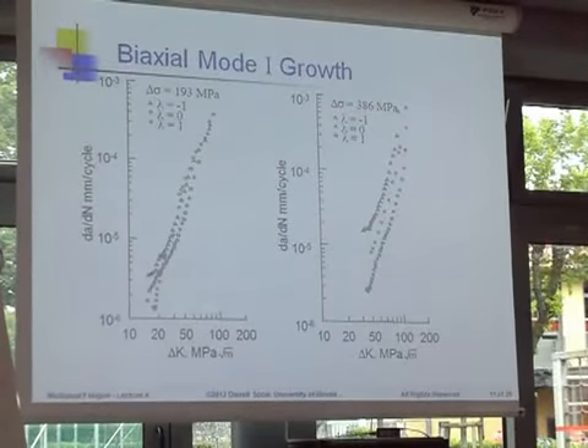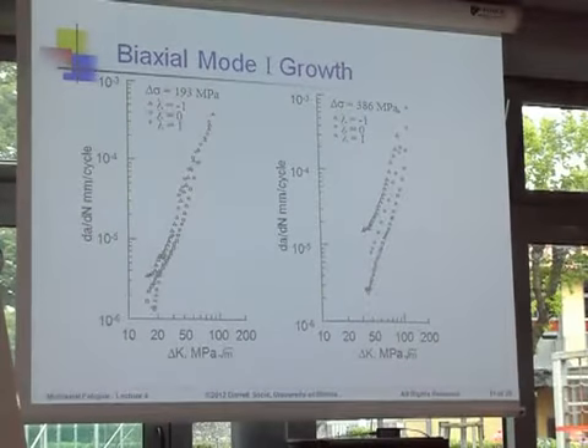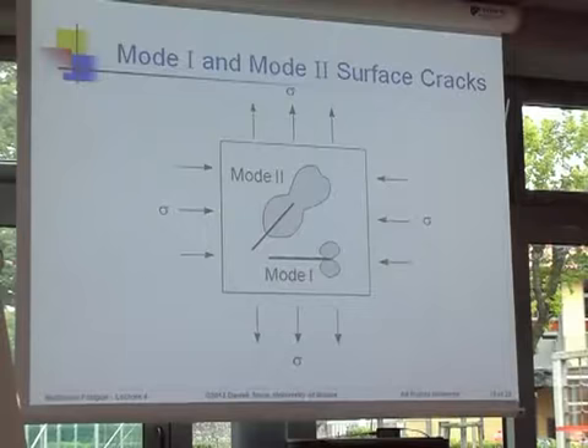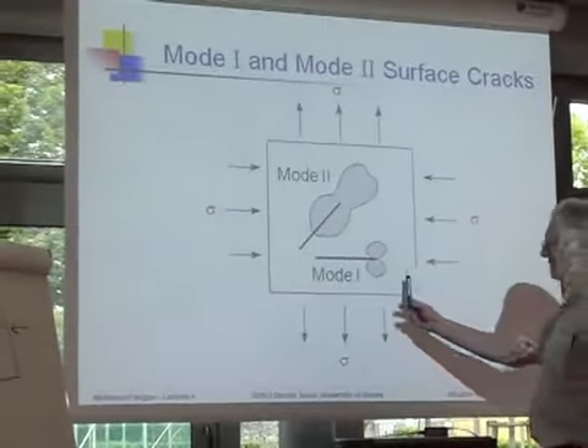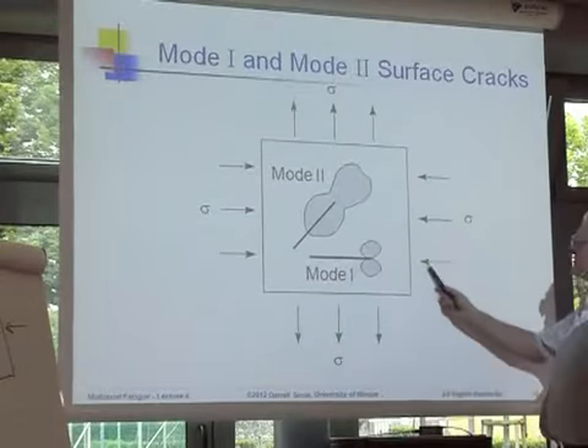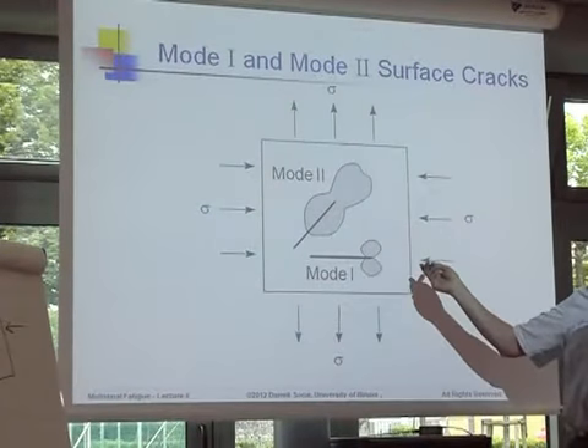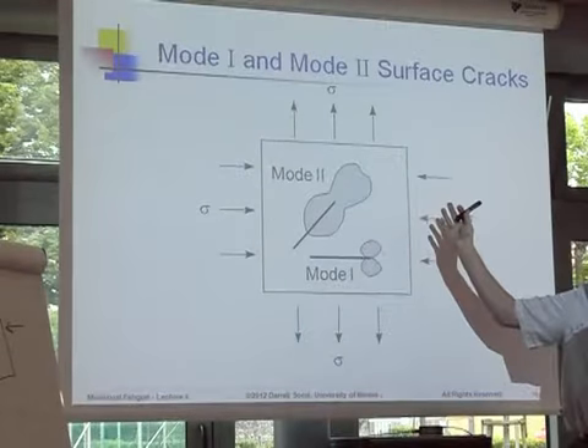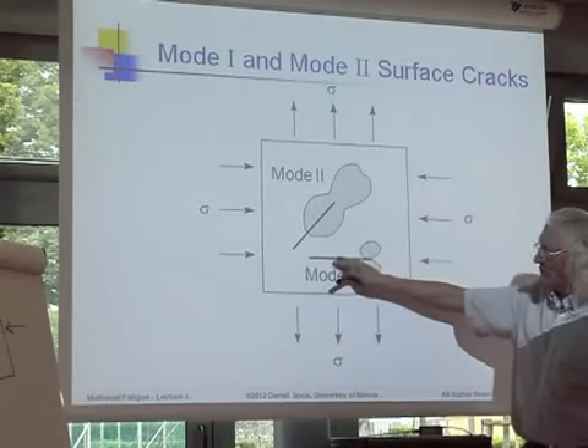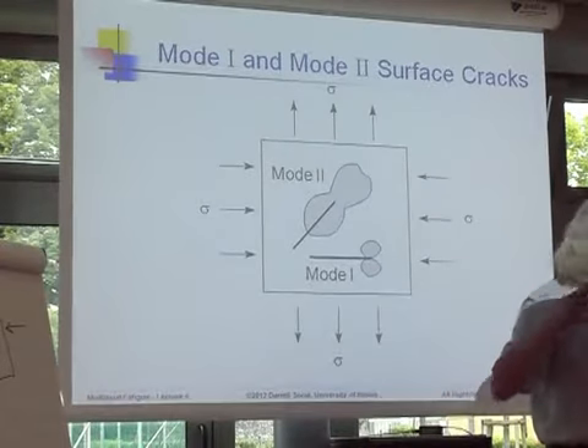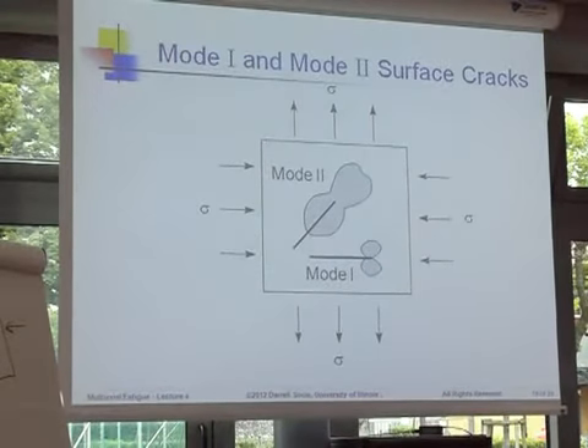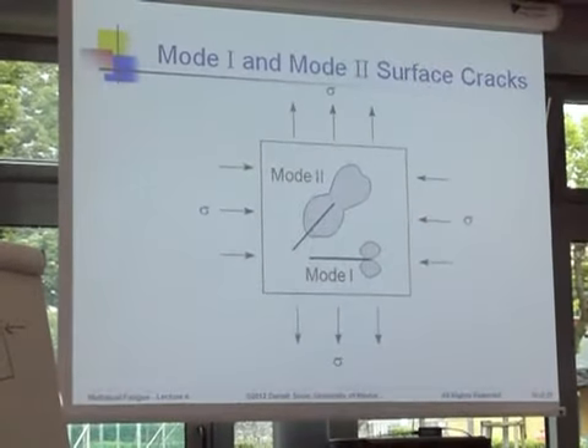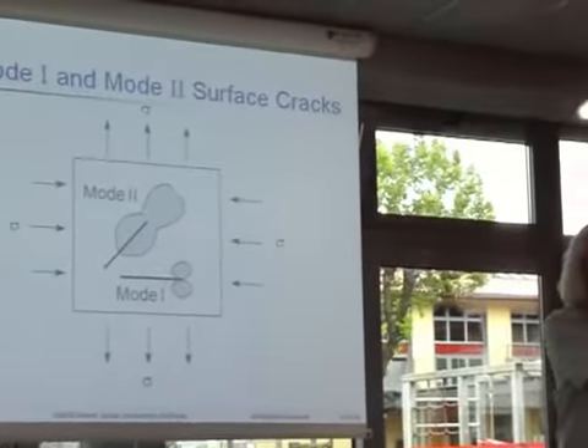So I think it is safe to say that if I look at mode 1 growth, just mode 1 growth of this crack, this stress doesn't matter. And there's almost no research anymore in this area. This stress for the growth of a mode 1 crack doesn't matter. So all of the effort in fracture mechanics modeling is into other modes of growth, mode 2, or the growth of a slanted crack in how it turns into a mode 1 crack. But the growth in a mode 1 crack, there's no effect of the so-called T stress.